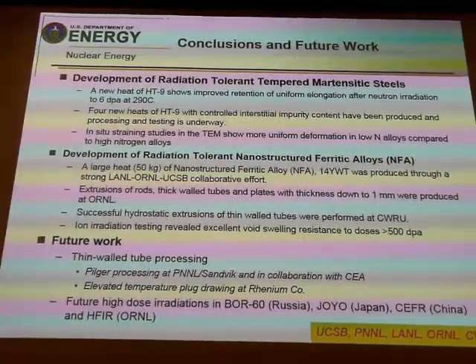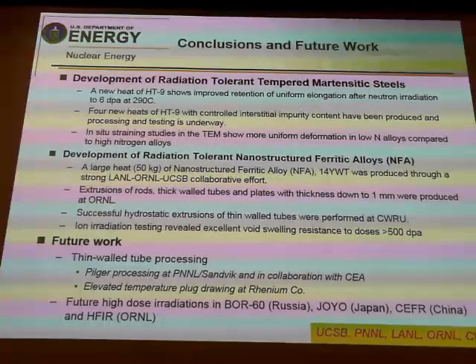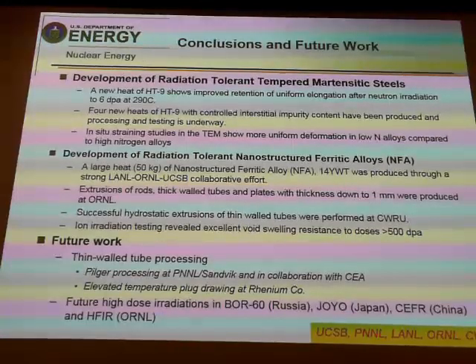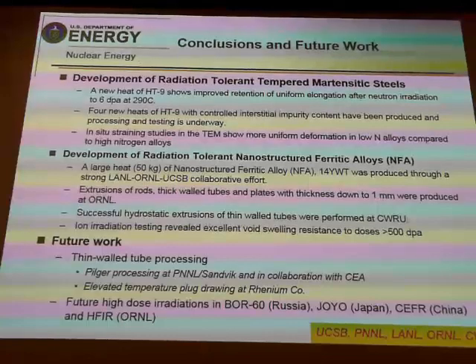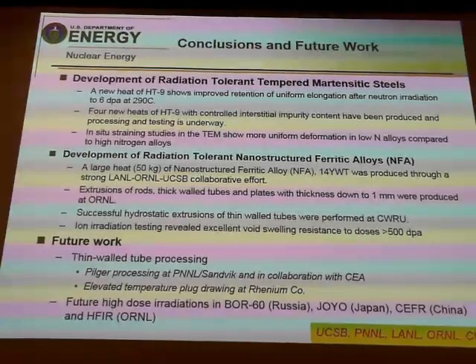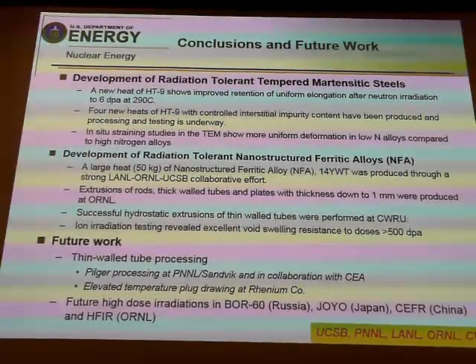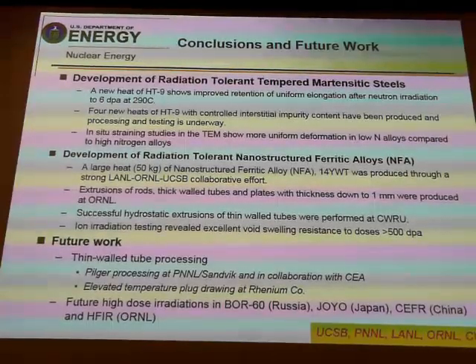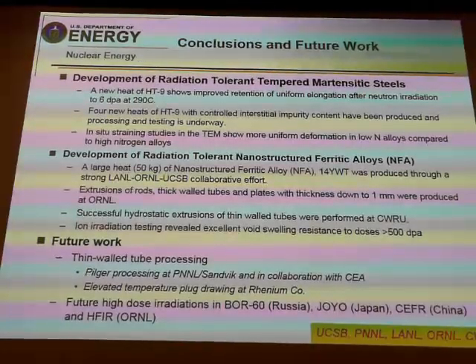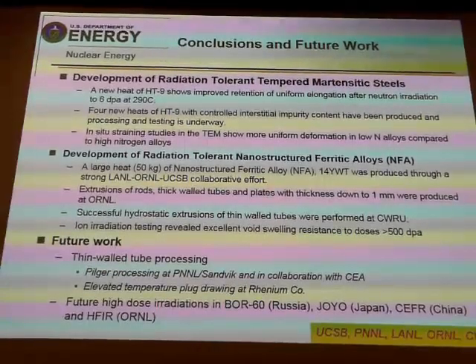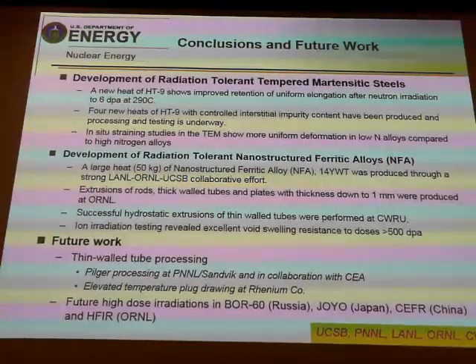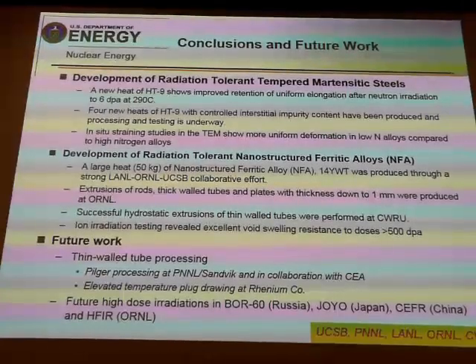One of the problems that's sneaking up on us with ODS is that you get ballistic decomposition of the ODS, which releases free oxygen into the material. And there's been some observations where you form very hard oxides because you now have free oxygen migrating in the material, and that also changes mechanical properties. So one of the questions at these high doses is whether the ODS can itself sustain the radiation damage.